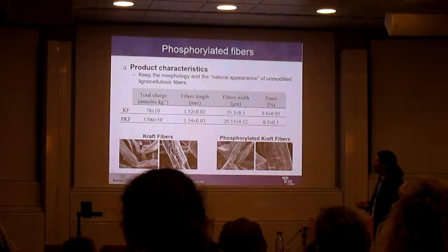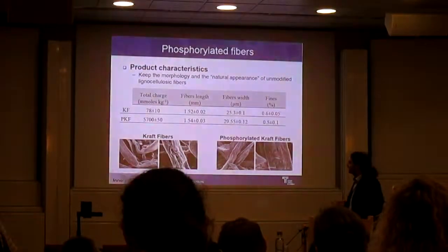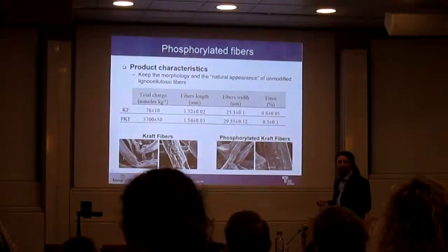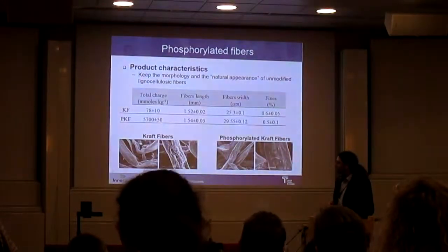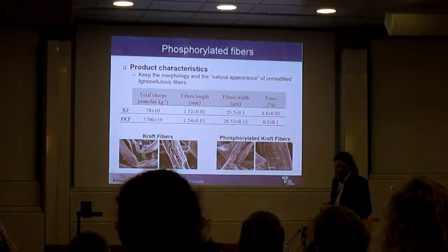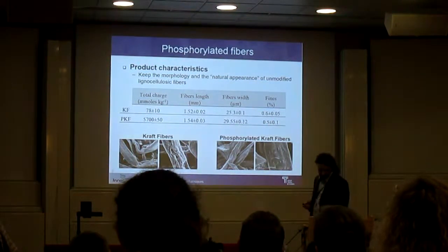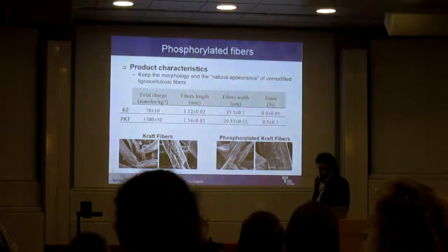We see the originating kraft fibers have less than 100 millimoles per kilogram of negative charge. After the reaction, we can put up to 6,000 charge.